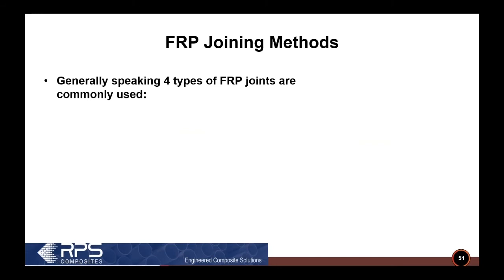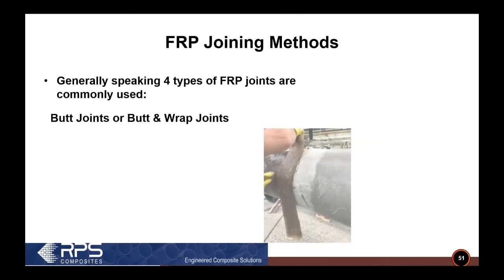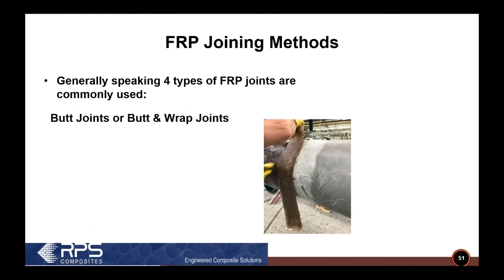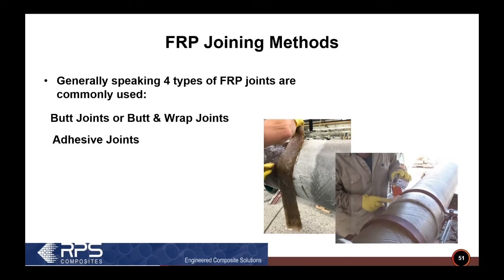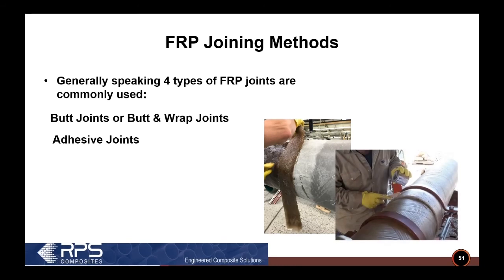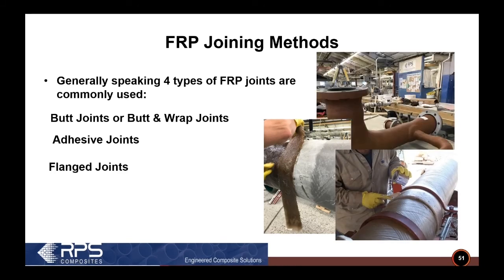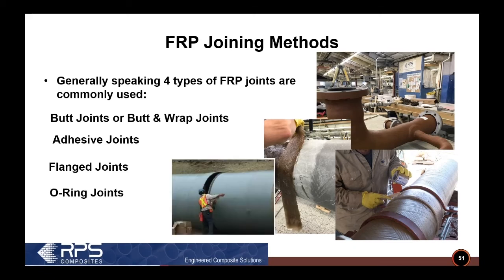And when it comes to joining methods, there are actually 4 types of methods we use. So we use something called butt wrap joints. Those are by far the most common type of joint, where we actually laminate the 2 pieces of pipe, or the pipe and fitting, together. There's adhesive joints where we bond the 2 pieces together. There's flange joints where we leave it up to you in the field to bolt the pieces together. And there's O-ring joints where we slip the 2 pieces together and then the O-ring seals the piping.